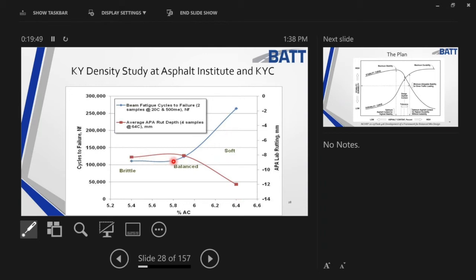I would challenge you though that this mixture at 0.5% more asphalt is much better than what you had before. It is more compactable. You do have more glue. These tests may not pick up on it, but if you threw it in something such as a Cantabro test, you'd find out you have better adhesion. So let's look at what the theory is on this one and what they call the plan.